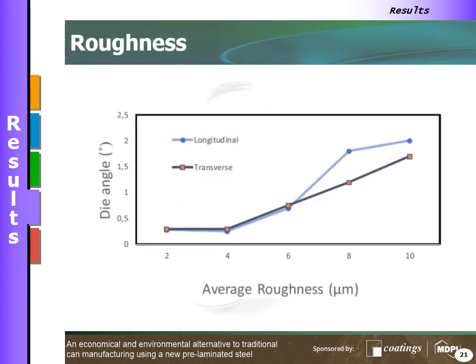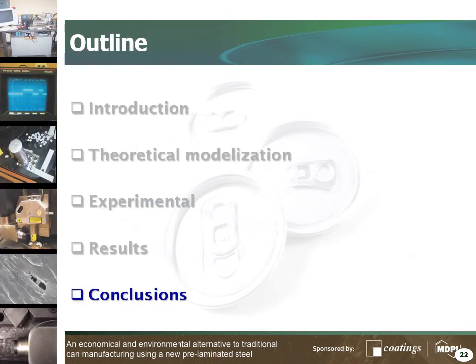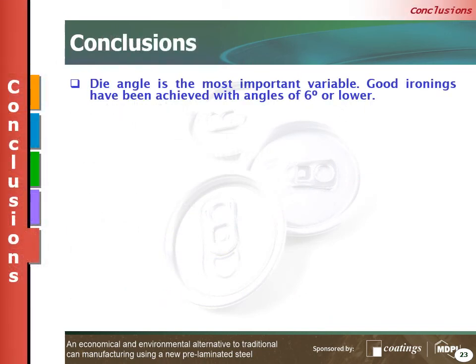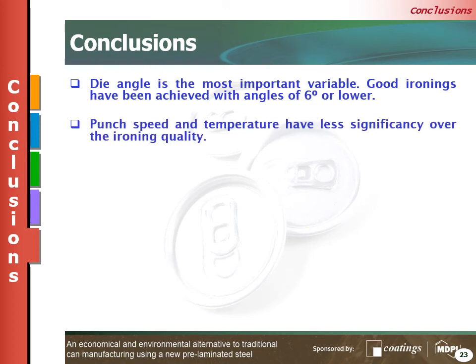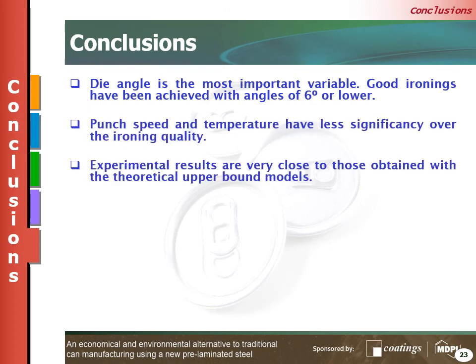And after some roughness tests made to strips, it's possible to see that angles below 4 have great surface. The conclusions. The die angle is the most important variable. Good ironing have been achieved with angles of 6 degrees or lower. Punch speed and temperature have less significance.